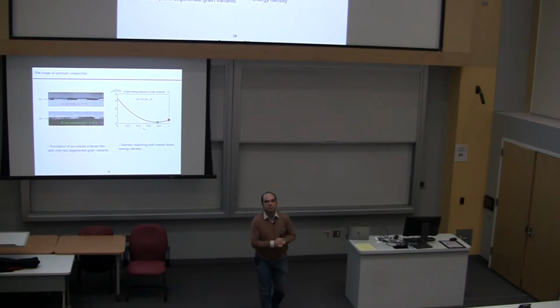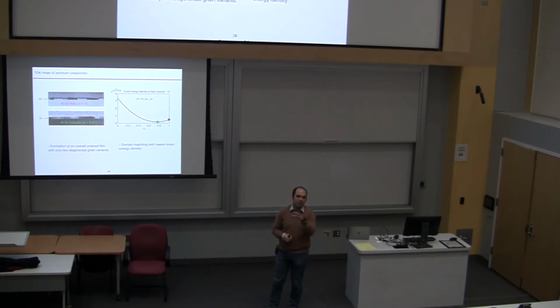Yes? How was this graph calculated, the strain density, full strain? Yeah, so basically you calculate with the Poisson ratio, if you allow things to strain from one side and then expand from the other side. So there are actually 3 terms in that calculation, the self-strain and the interface strain. And then you try to minimize that. So they are actually famous from the 80s and 90s, and even if you look in our papers, there is a supplementary that explains that. But it's a very simple calculation. The one that I showed you is a high school student calculation. Once you have the code, the MATLAB code, you can actually figure it out.